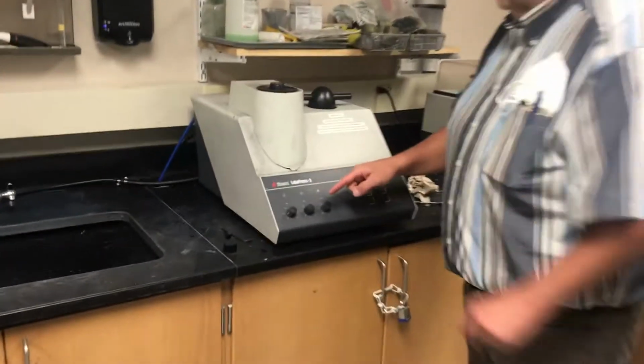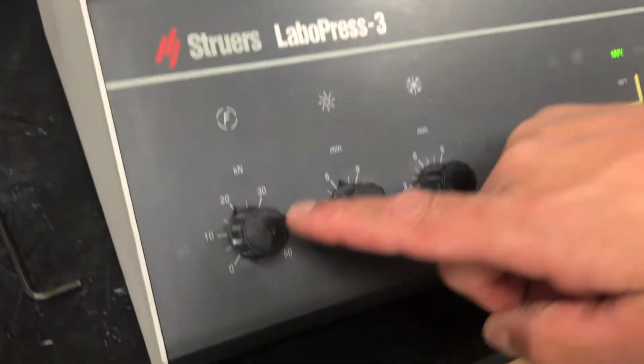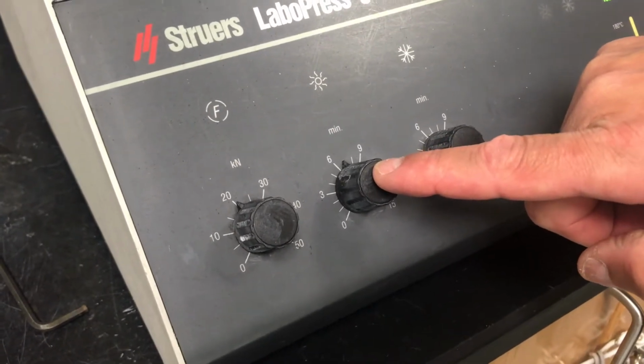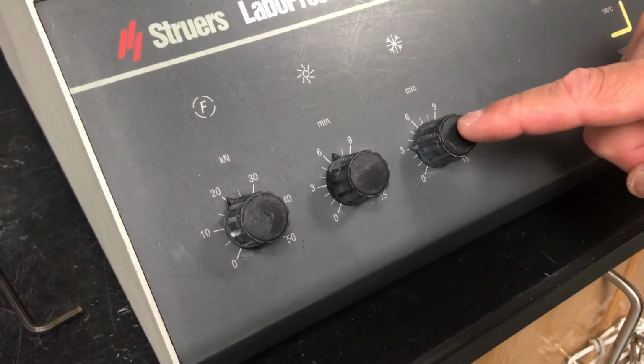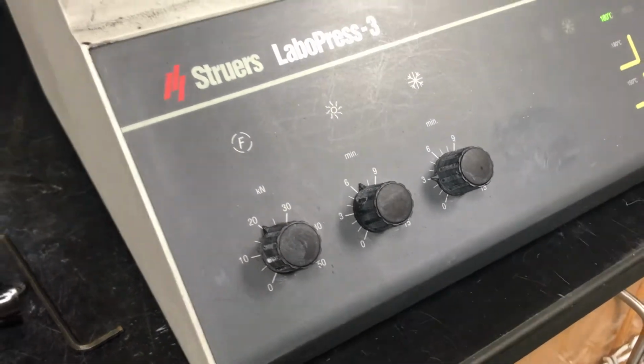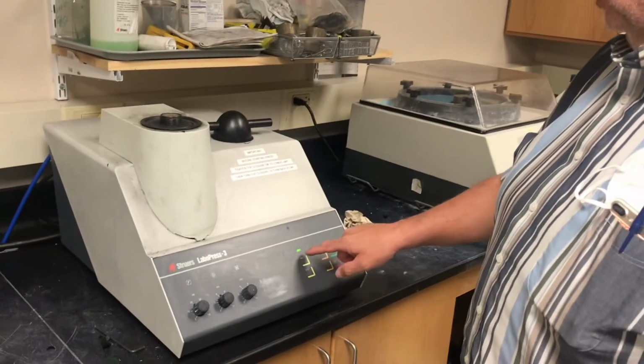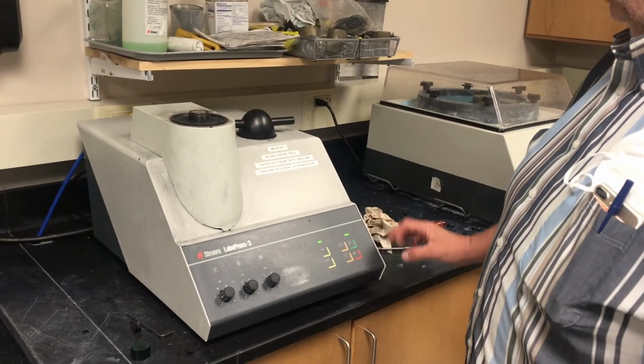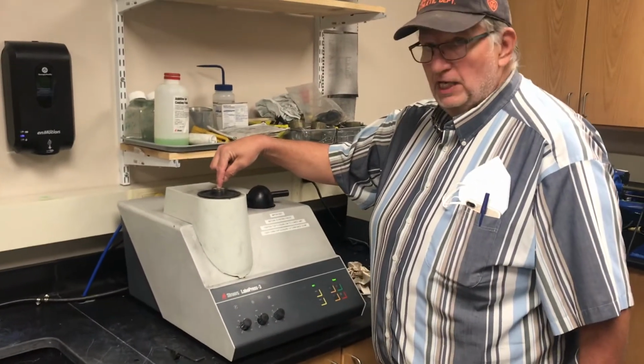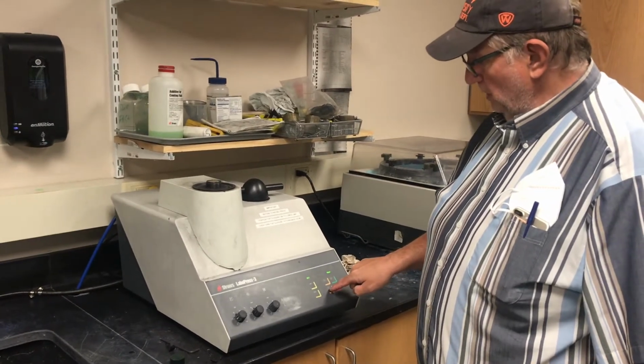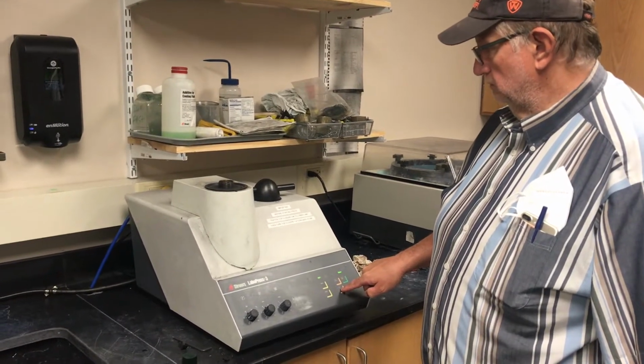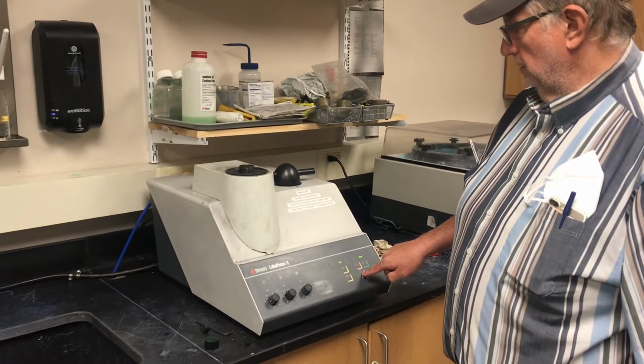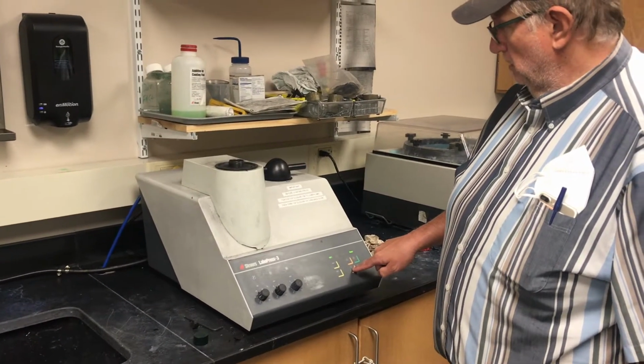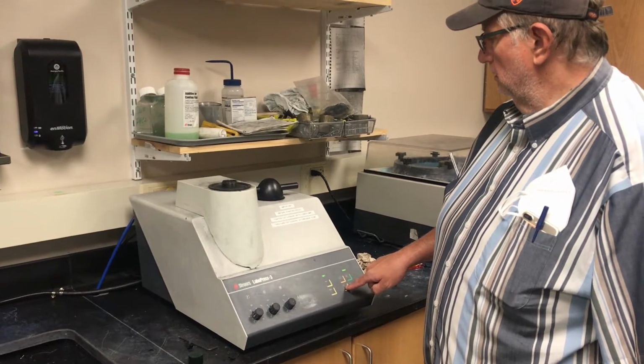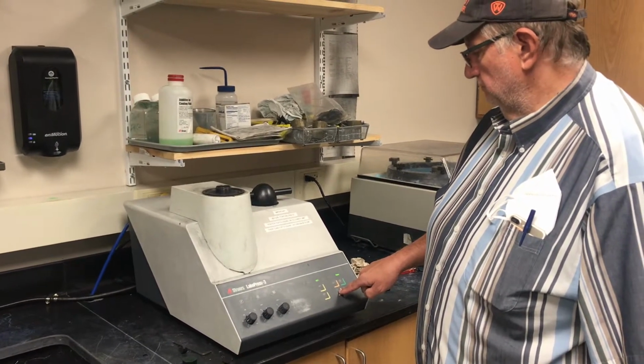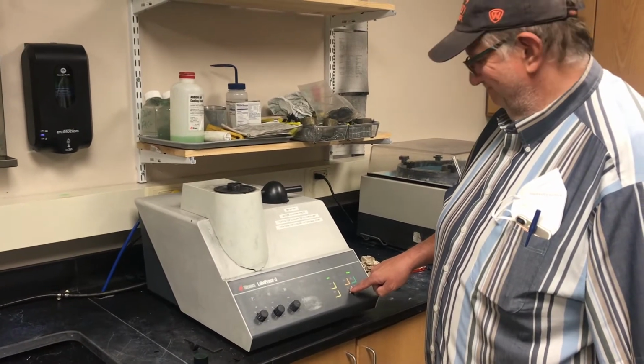If you'll notice, the force is set on 20 kilonewtons. The heating operation is on 7 minutes, and the cooling operation is on 3 minutes. That should be about right. The temperature should be 180, and nothing should change there. Once you place your sample on the stage, lower the stage right here, down into the press. It takes about 10 seconds. Seems like more.